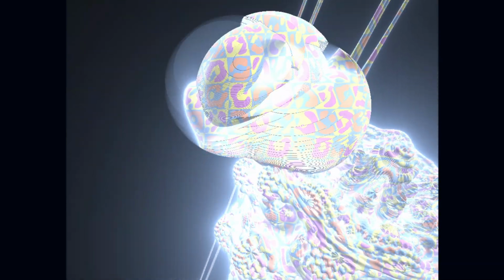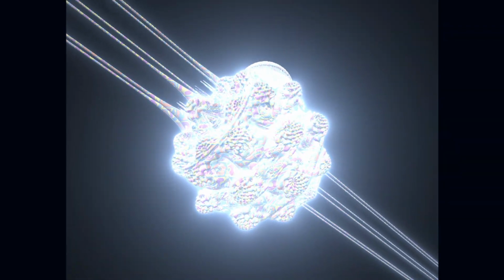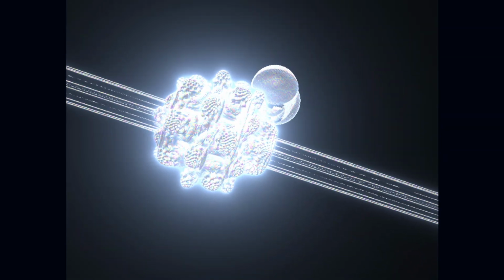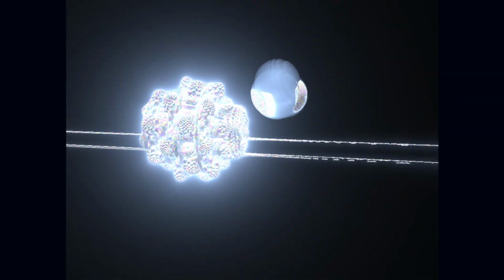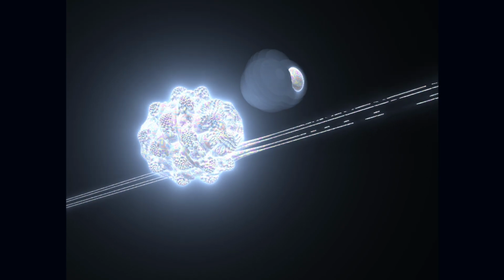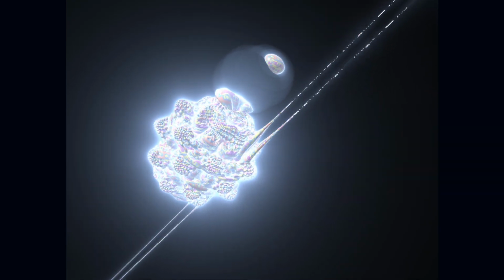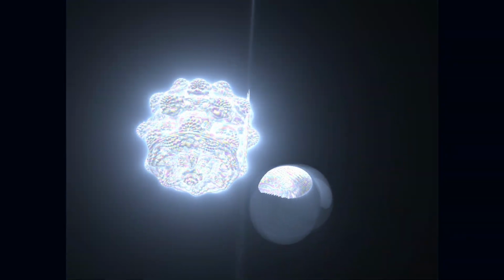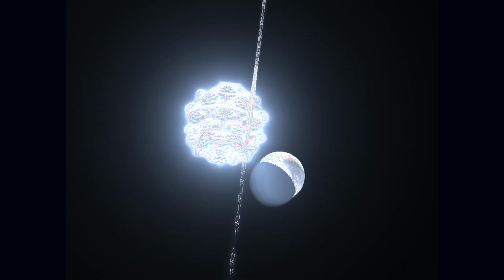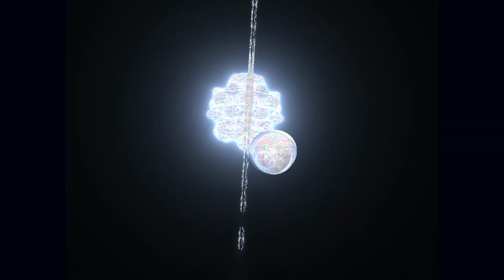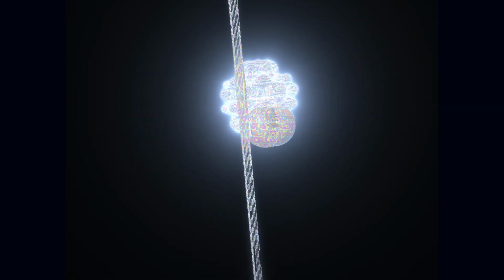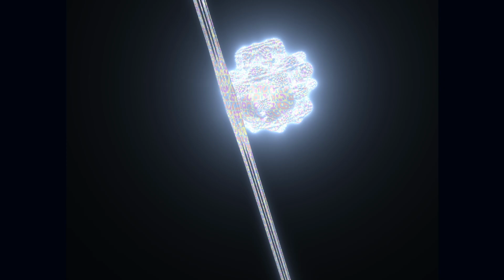So it's not just a subtle effect then. It's a measurable additive increase to the electron's mass, even in that intermediate coupling regime you mentioned for CsPbBr3. Definitely. In CsPbBr3, the bare band mass is about 0.17 times the free electron mass, and alpha is around 1.81. The Feynman model predicts a renormalized Polaron mass of about 0.24 times the free electron mass. That's a noticeable increase, like what, 40, 50% heavier? Roughly, yeah. It's significant.